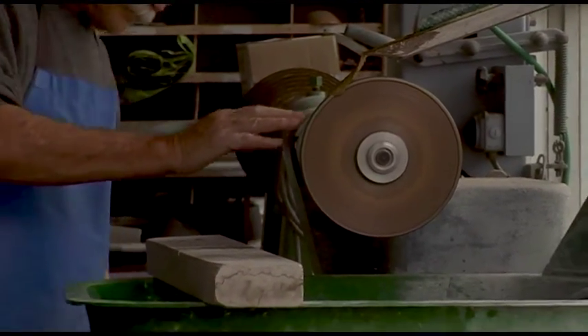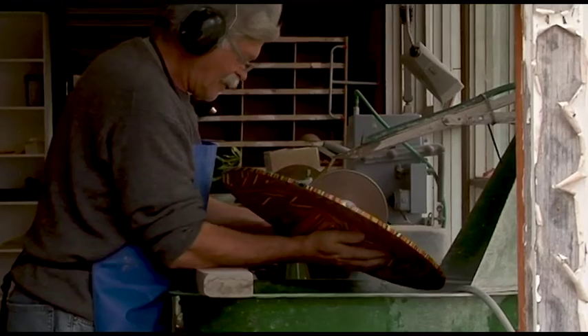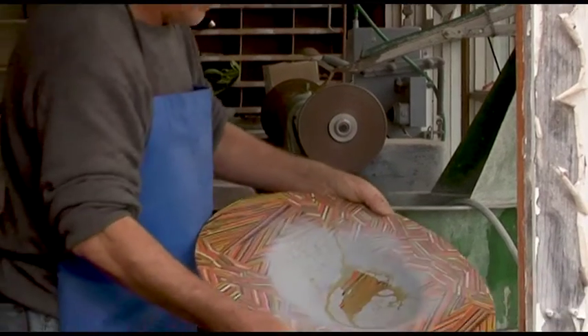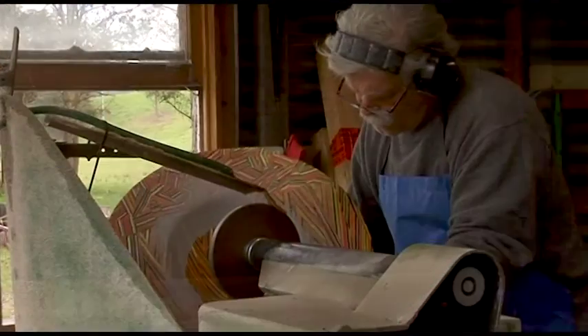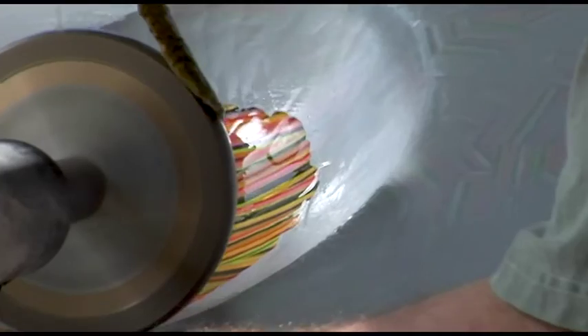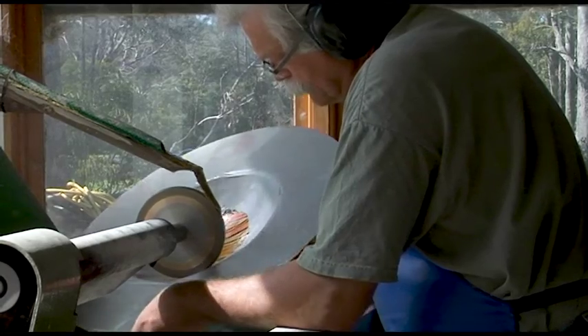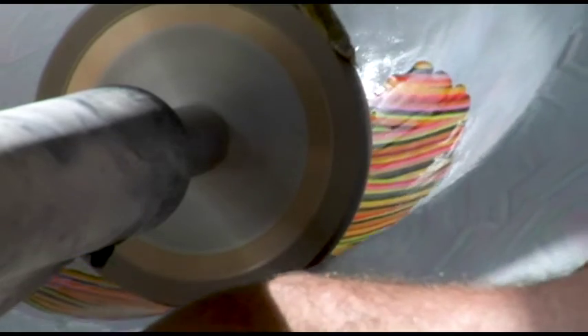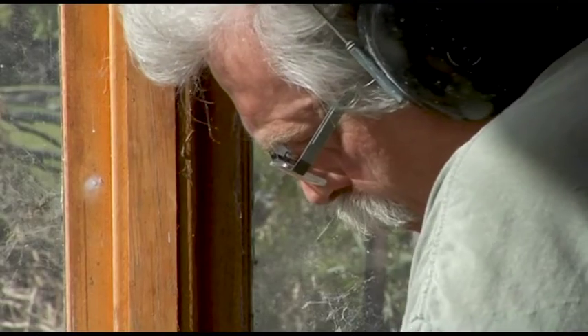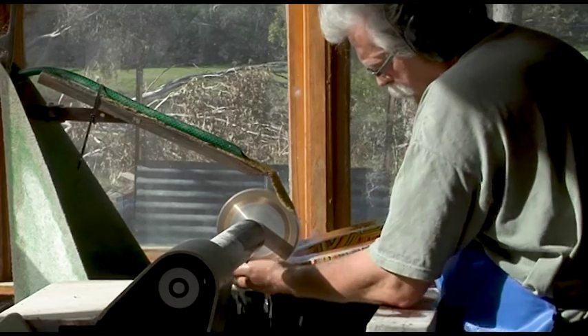First I cover the piece with a fine layer of paint — I use a rust paint. It shows me exactly where I am with my grinding wheel when I grind over the piece. With the grinding I go back to the core of the glass. The upper layer of the glass has been through the firing process and has therefore become a little bit unclear. So by grinding away the smudge and the outer layer of that first surface, I gain crisp colors and crisp lines again.